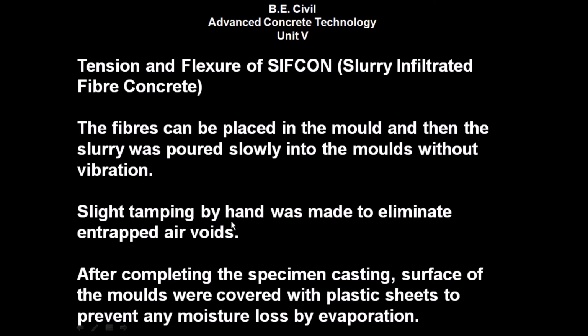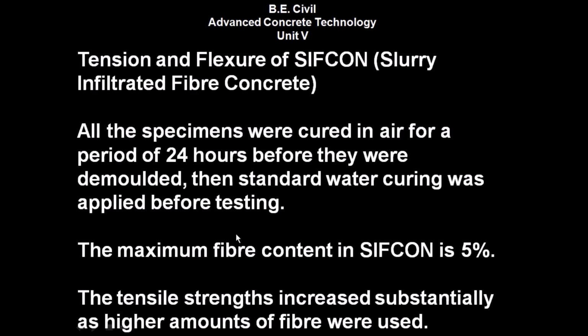Slight tamping by hand was made to eliminate the entrapped air voids. After completing the specimen casting, the surface of the molds were covered with plastic sheets to prevent any moisture loss by evaporation. All the specimens were cured in air for a period of 24 hours before they were demolded. Then standard water curing was applied before testing.